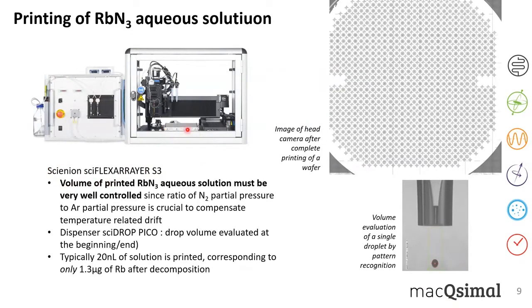You can put here a whole wafer, and you have here the reservoir of the liquid or the aqueous rubidium azide solution, and somewhere here is a very tiny nozzle. I have here a bigger picture of the nozzle that ejects a droplet, with a volume of some 100 to 300 picoliter ejected per droplet. So with this dispenser, or with this filling machine, we can very well control the quantity of rubidium azide that is spotted into each cavity.